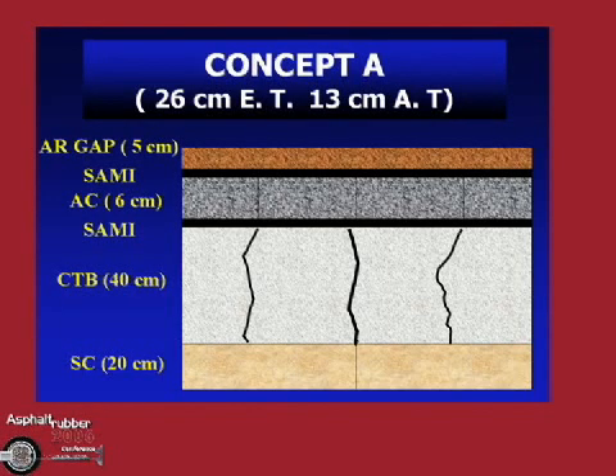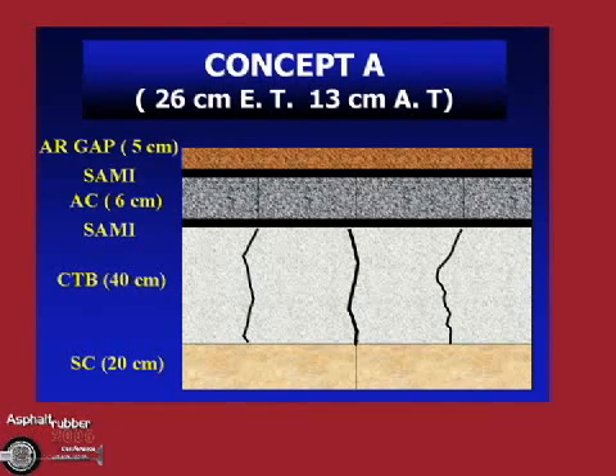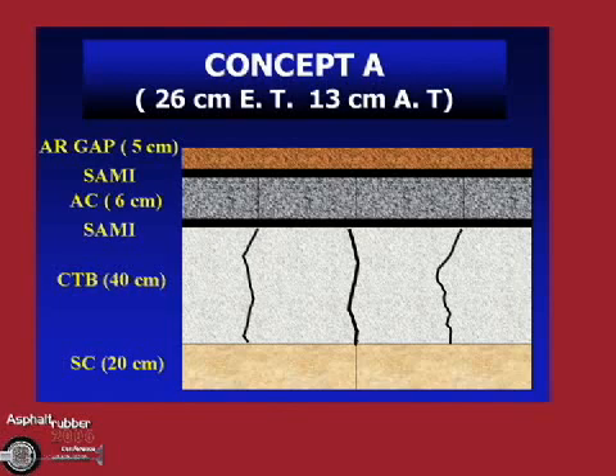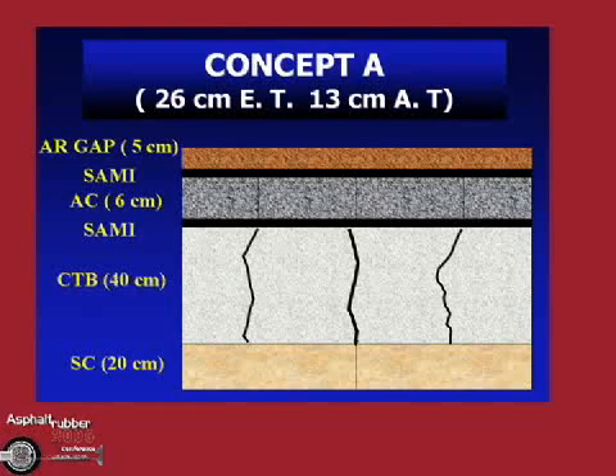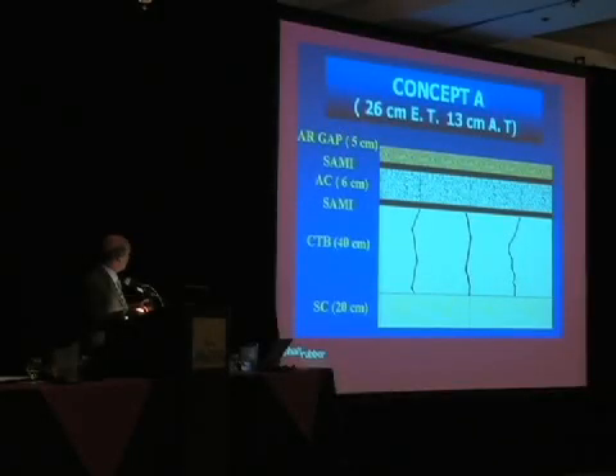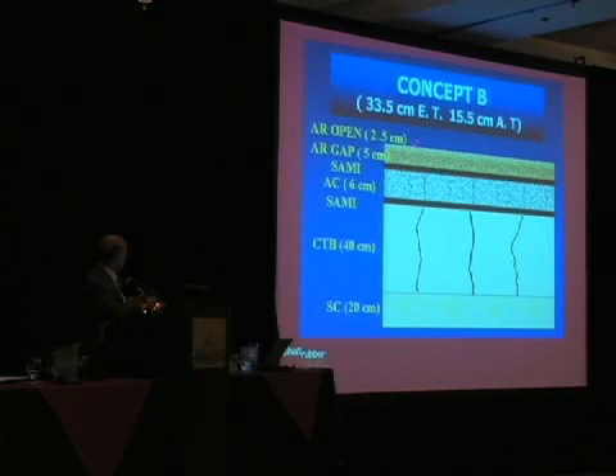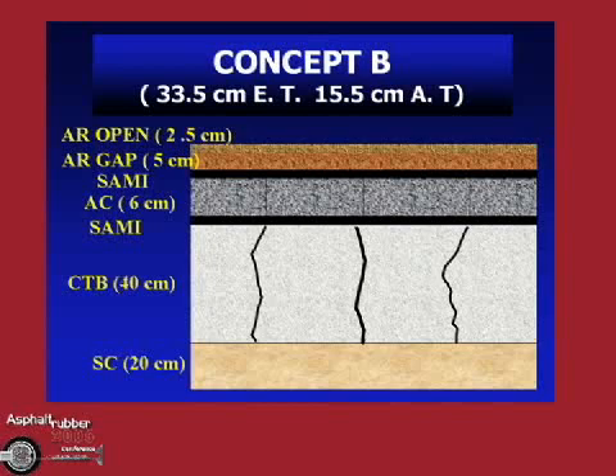The resistance, the strength, is given by these layers. And then just consider putting on top whatever it takes, the minimum asphalt rubber combination to resist the crack propagation. In this case, we consider a SAMI, 6 centimeters, another SAMI, and 5 centimeters gap graded, which gives 13 centimeters of actual binder layers, equivalent to 26. Or in another case, on a freeway, we can put the open grade, and in fact, it's like having 33 centimeters of asphalt rubber in equivalent thickness, but in fact, we have 15.5.